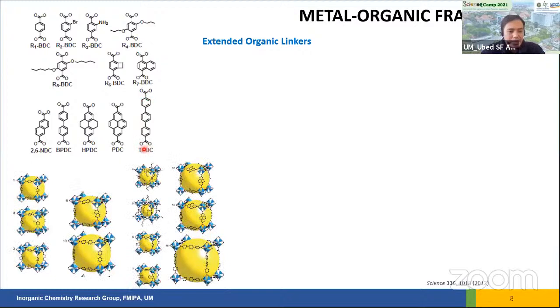As a result, we can see here, if we use only one benzene ring, the pore size is considerably small. But if we use 2 phenyl rings, the pore size is bigger. Remember that these yellowish balls are dummy balls, meaning that there is empty space inside. If we use 3 phenyl rings here, we can have a bigger pore size, meaning that we can modify the structure of the MOF on our own.